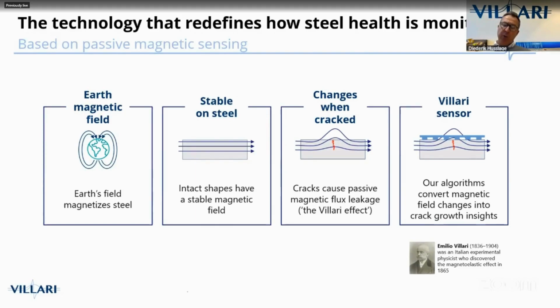What we have found out, and this is what we have patented essentially, is that we have found a correlation between the change of that magnetic field and the force that is happening with the various stage of cracking. So we're not only detecting cracks and the crack propagation, but I think most interestingly, we already see the early signs of plasticity deformation and elasticity changes into the steels, which are the initial point of a crack. And we are able to show you that real time into a dashboard.